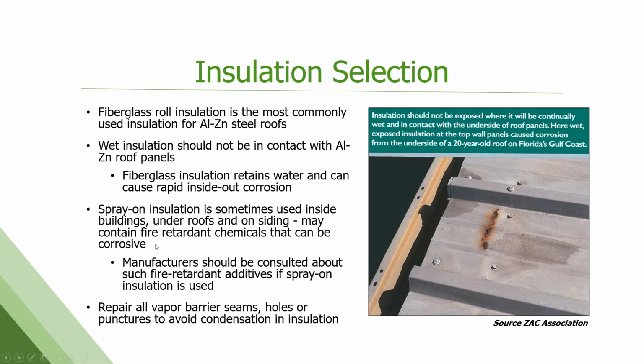Insulation. Fiberglass roll insulation is commonly used with this material, and that's fine. You just want to make sure it can't get wet, because if it's wet and sitting in contact with the panel, you actually have inside out corrosion that occurs. The corrosion will start on the back side of the panel and work itself out to the exterior over time. Spray on insulation can be used. We've seen that used well, but you've got to make sure they don't have a fire retardant chemical that contains copper, which is then corrosive to the aluminum zinc substrate. You want to repair all vapor barrier seams and holes anytime you see them and do regular maintenance.